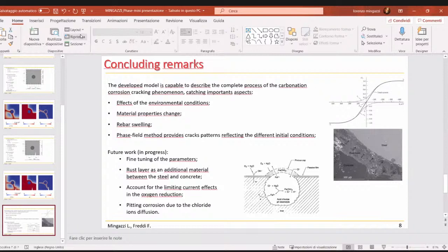Moreover, material property changes are introduced, for example, for the change in porosity, for different material properties of the materials. The rebar swelling is introduced and used as a loading parameter instead of imposed displacement on the steel rebar. And the phase field method provided results which are actively affected by the different material and environmental conditions we set for the different tests.